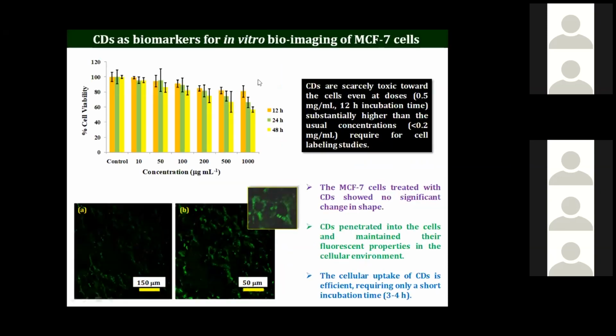Now we look at cell viability also. When you want to look at cellular imaging, the material should not be toxic. So we look at cell viability for different durations of time, and that tells us whether it can be used for bioimaging. We used MCF7 cells treated with CDs, which showed no significant change in shape. The CDs could penetrate the cells and maintain their fluorescent properties—that is very important, as only then can you use it for bioimaging.